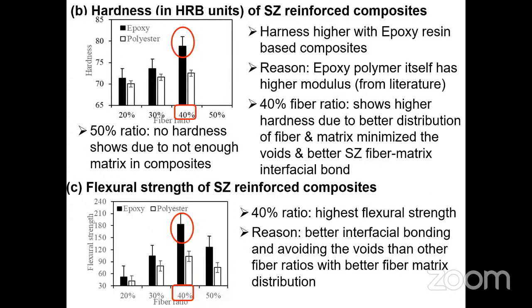In this slide, you can see the hardness of Sansevieria zeylanica fiber reinforced composites and flexural strength test results. In hardness test results, the 40% fiber ratio has the highest hardness, and epoxy resin has the highest hardness level. The reason is the epoxy polymer itself has a higher modulus.